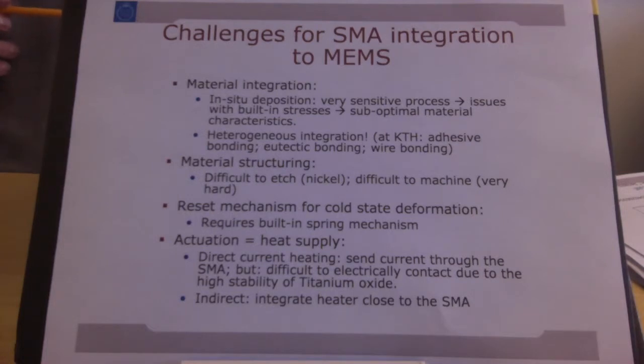For one, it's a very conductive material, so you'll need a very high current to create the heating. You're going to need a lot of power to do that. And secondly, just electrically contacting titanium nickel is difficult, because the titanium forms an extremely stable oxide immediately when it's in air. So you need to get rid of that oxide before you bond a contact wire to it, and that's not easy, and it's not a standard process either. So that's troublesome. Indirect heating means that you integrate a heater structure on or near the SMA itself, and you use the heat of the heater to indirectly heat the SMA.